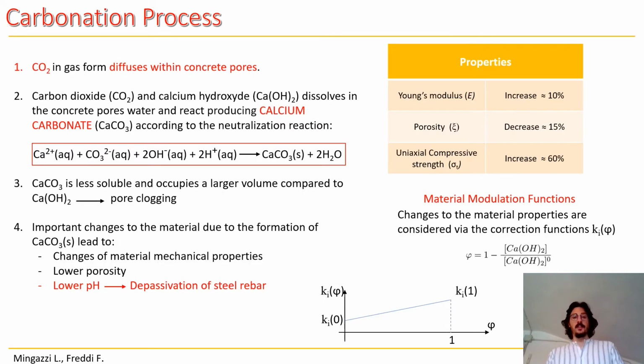The carbonation process starts with the carbon dioxide diffusion within the concrete pores in gaseous form, and eventually it dissolves into the pore water and reacts with the calcium hydroxide present in the cement paste to form calcium carbonate, according to the neutralization reaction reported in the presentation. The calcium carbonate is, however, less soluble and occupies a larger volume compared to the calcium hydroxide, which leads to the phenomenon of pore clogging.